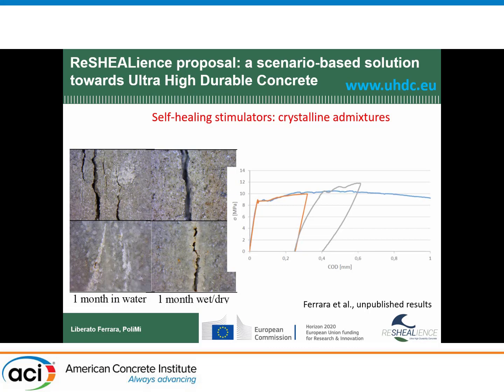But what we are going to show now, this is the reference curve monotonically tested, whereas we pre-cracked the specimen, we unloaded, we cured for 1 month in water, and after that we tried to reopen the crack. And on the second load cycle, we went even a little higher with the stress. So this is probably because these products which grow into the crack try to expand a little bit into the crack. So there is some chemical pre-stressing, we call it that, and we want to demonstrate this.